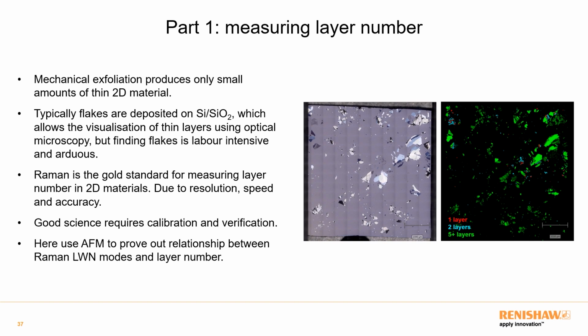So normally what people would do, for good science, is find some flakes of varying thicknesses. They would determine the thicknesses using the AFM directly, and then measure the Raman at those locations to calibrate the thicknesses. There's loads of work in the literature with this being done, and it's very easy then to go back and use the Raman, which is the faster method, to determine layer number.